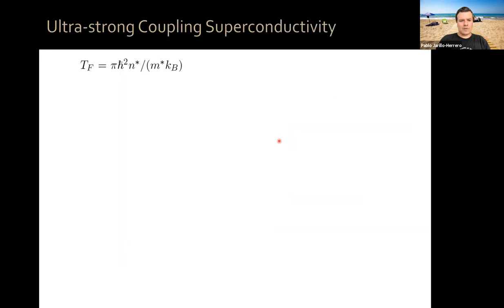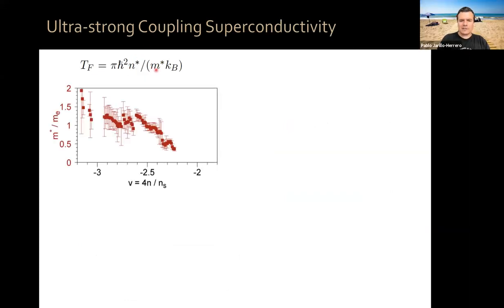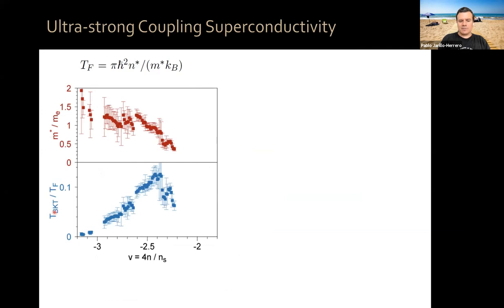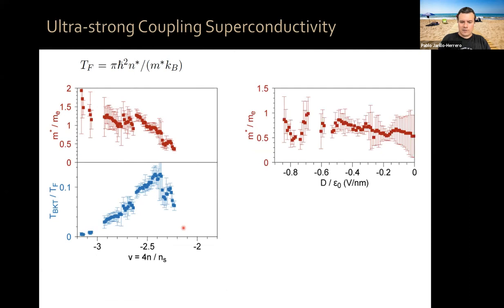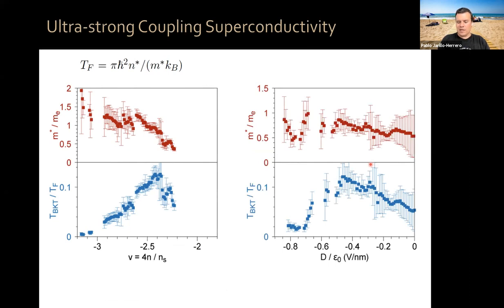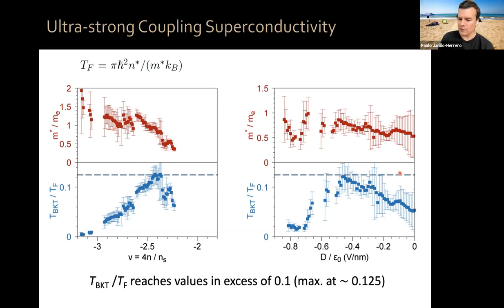So the Fermi temperature is given by this expression, and we know the density of carriers. We can measure the effective mass, which is here as a function of filling factor at a certain displacement field. So we can extract this T_BKT, which we also measured, I just showed you before, over T_F, and these are the curves as a function of displacement field. We can do the exact same thing as a function of filling factor, and we can measure T_BKT over T_F as a function of displacement field. And as you can see, this actually corresponds to 0.125. So T_BKT over T_F reaches values well in excess of 0.1, with the maximum coinciding within error bars to about 0.125.